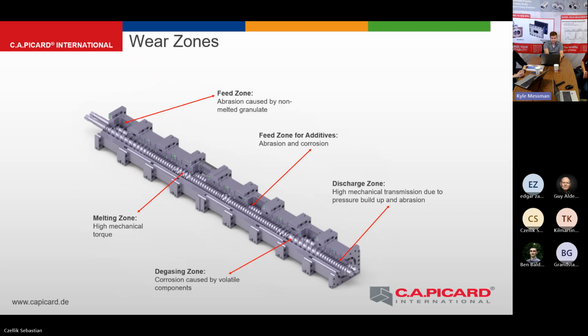And going even further down, we have the degassing zone. In that zone, we mainly see corrosion because we have volatile components or steam that is going out. And last but not least is the discharge zone, where we often have heavy wear because we have extremely high pressure. Sometimes even the shafts are pulled apart at this position and run against the liner.